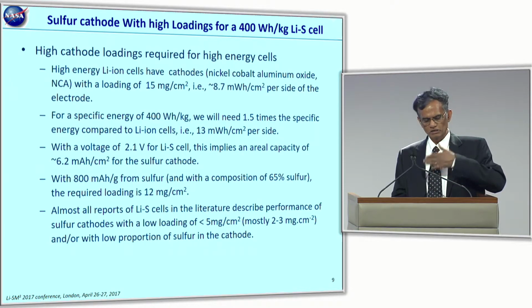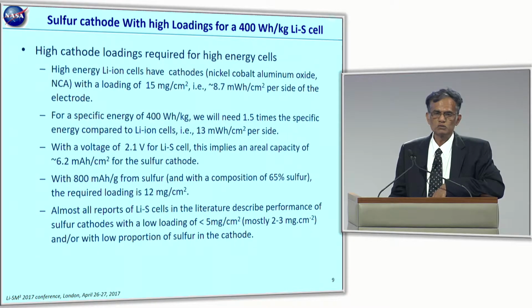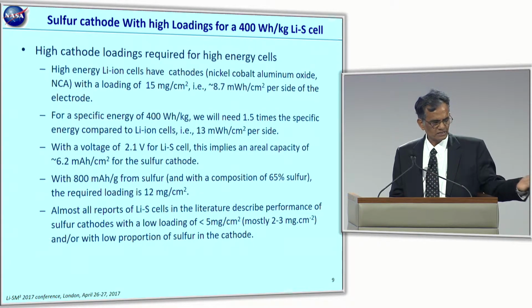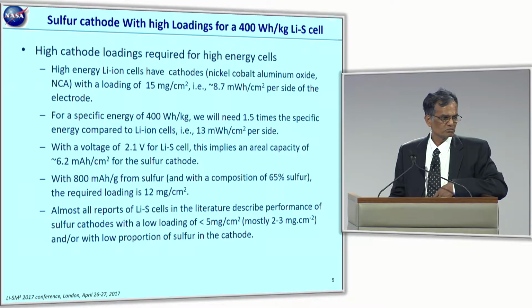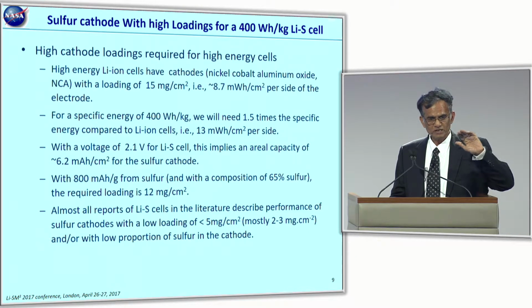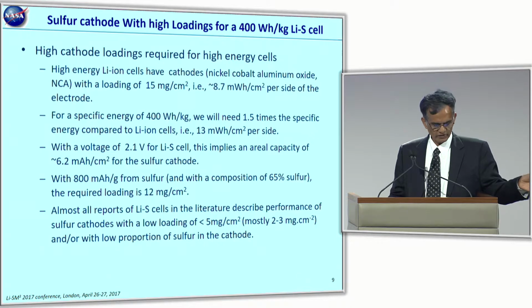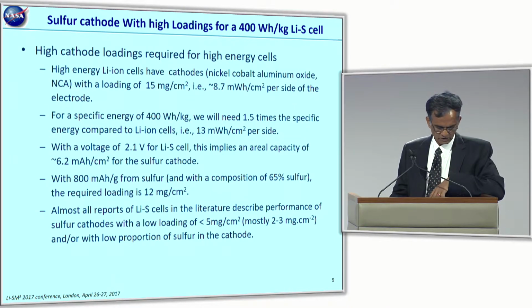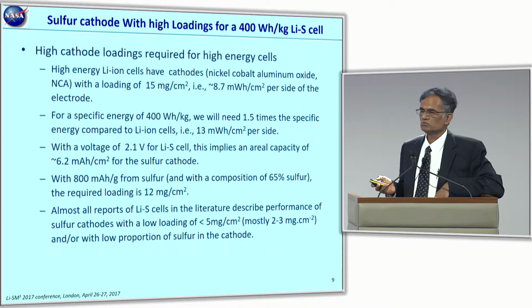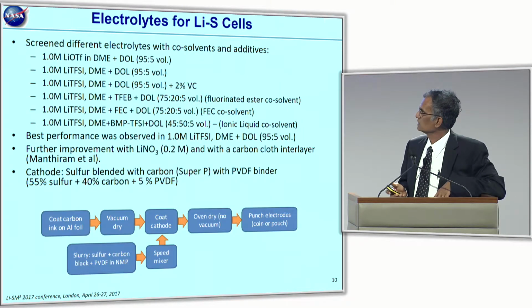And then again, running the numbers, assuming that we get about 800 milliamp-hours per gram, and with a composition of 65% sulfur in the cathode, we are talking about at least a loading of 12 milligrams per square centimeter. Actually, I saw numbers yesterday on the tour that I took, much lower than that, which Oxis is shooting for right now. But granted, there is some benefit coming from the lithium anode compared to the graphite, anything in the range of 10 to 12 milligrams per square centimeter will help us get to 400 watt-hours per kilogram. And that is a challenge based on what we know in today's lithium-sulfur world.